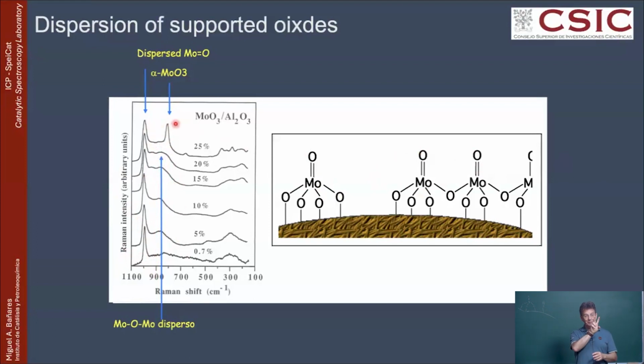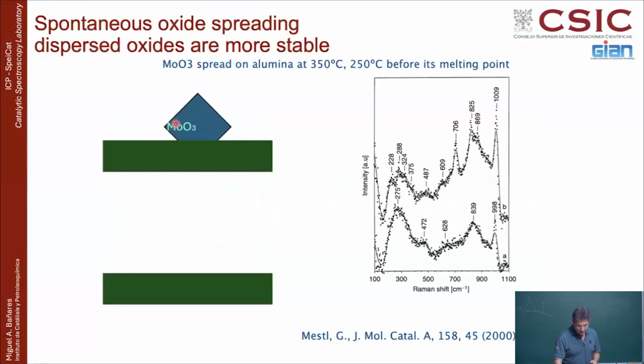So you have these crystalline molybdena bands over there, and then the other ones. So you know that this one is crystalline and these are dispersed, just by comparing hydrated with dehydrated. You are getting a lot of information from things as simple as that. You can even look at what is happening with the supported oxide. Sometimes when you are making a dispersed oxide, you don't do fancy things. You simply mix two powders, like alumina and molybdena, grind them and heat. And this is a very old paper.